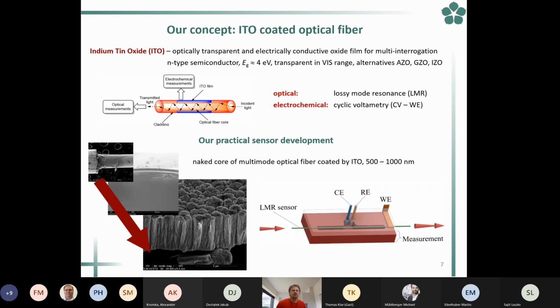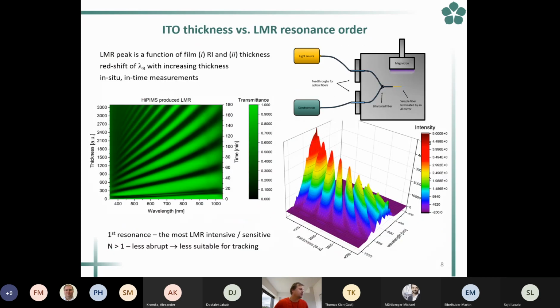So finally, we have the film which is able to produce the lossy mode resonance, the optical way of detection. But this indium tin oxide, usually known as ITO, is also electrically conductive. So you can use it also as an active electrode for electrochemical measurements. And practically the arrangement you can see here. So we have the optical fiber. By the light coming through it, we are able to do the optical detection, and using the electrochemical compartment, we are able to detect some species also electrochemically. So one sensor at one time is giving us two ways of detection and two signals.